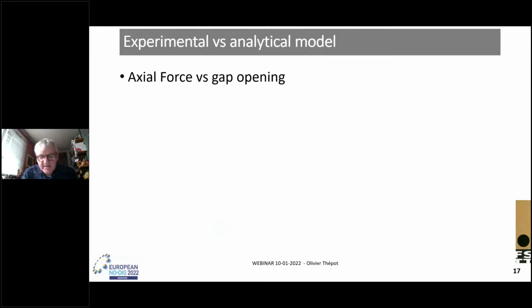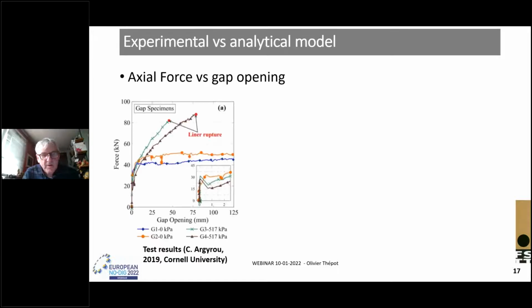We now compare the experimental result with our simple model. The graph on the left shows the tensile force versus the gap opening measured in 4 tests conducted at different pressures. At 0 pressure, the blue and the orange curves are quite horizontal. The tension force is almost constant. It does not depend on the opening of the gap, and it is almost equal to the value of the debonding force, which is here approximately 45 kilonewton.